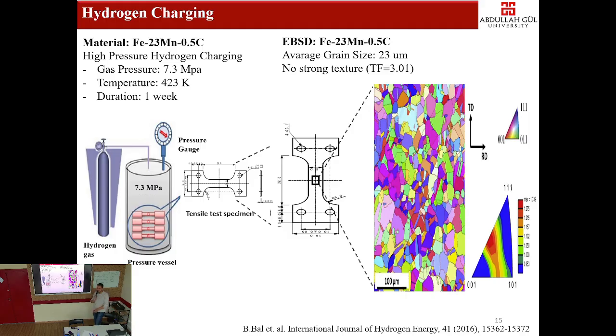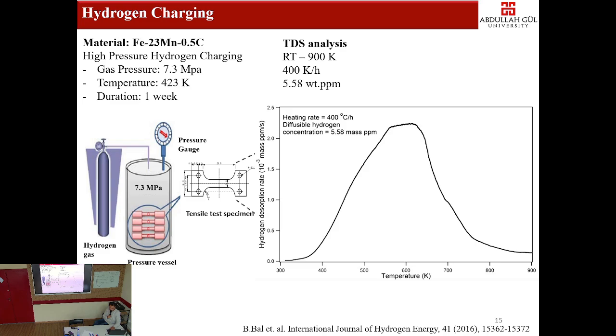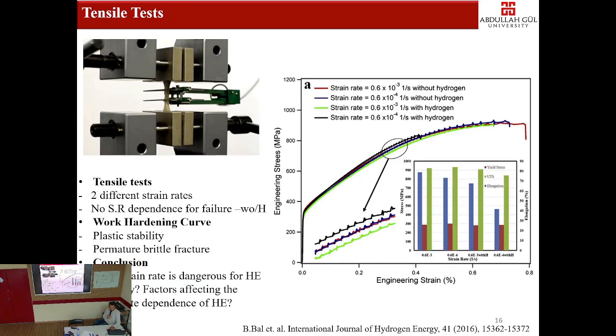I don't want to bother you with the experimental part because you guys have very good facilities. I just wanted to show you what we have done with experiments. This was during my time as group leader at Kyushu University. We had high pressure hydrogen charging, and we got EBSD. I just wanted to show you which capabilities we have experimentally. We did TDS analysis, measured the diffusible hydrogen concentration, and we had an in situ tensile test. This is just a representation.